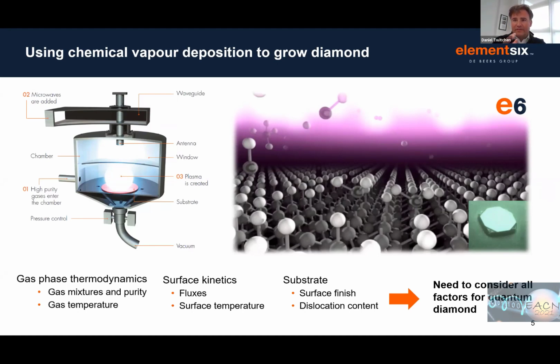The benefit of this environment is that you can start to think about doping. You can control the purity. You can add impurities into the gas phase for doping. So we're going to talk a little bit about silicon and nitrogen in a bit. We can add those deliberately into the plasma, and, not quite MBE-type control, but you can get layer by layer growth of these defects into the material, these color centers in the material.